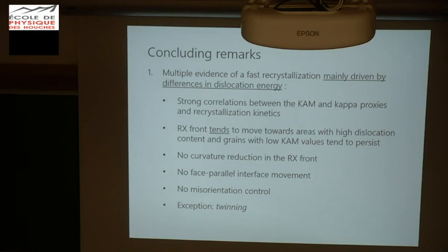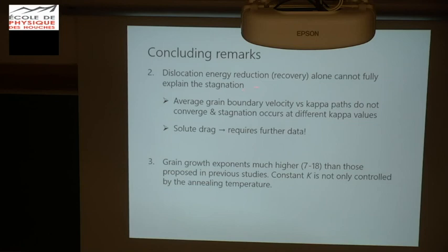We did not observe face-parallel interface movement in the experiments. Neither do we find misorientation controls, and the only crystallographic control that we found is that twinning exerts some effect on the final recrystallization fraction and explains some of the off trends we observe. Finally, dislocation energy reduction alone cannot fully explain the stagnation, and we